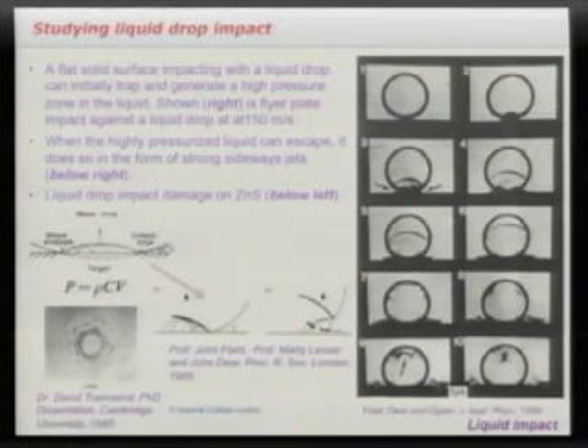So in my PhD, I was studying these shock interactions and trying to explain the damage that would be produced. And I had a colleague who's here today who was looking at the actual materials. And there were some quite exotic materials. I think at one point David was testing sapphire, but zinc sulfide was fairly commonplace. These are all special materials which were infrared transmitting window materials. And you can see that you get some interesting damage patterns from a single impact where you get a little fine array of cracks. And that's because the impact event is a very short duration loading of the structure, and in that short duration loading, the cracks can only grow a small distance.